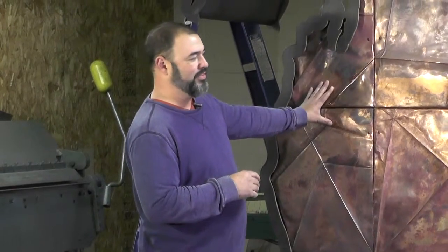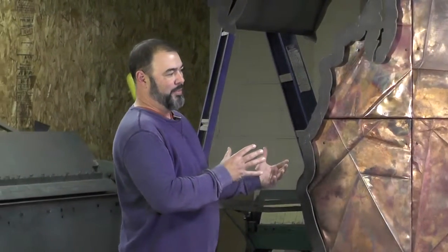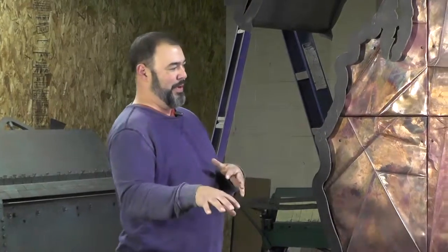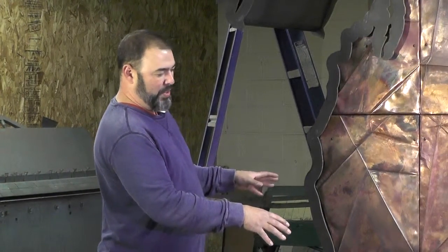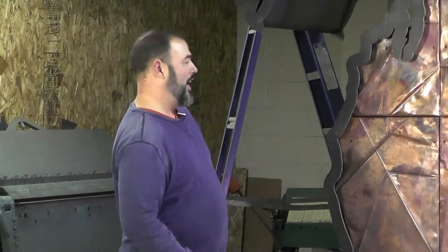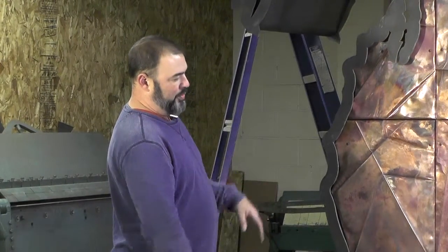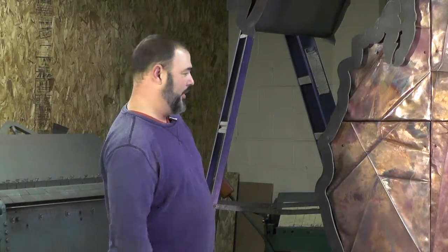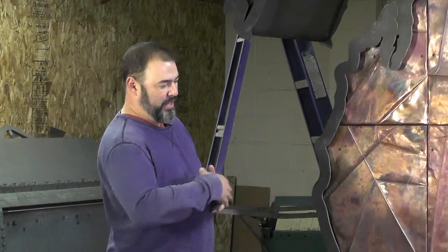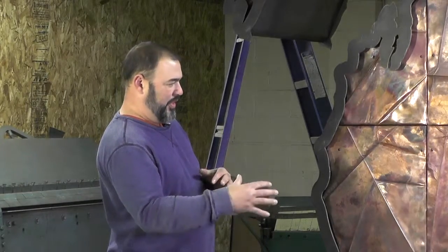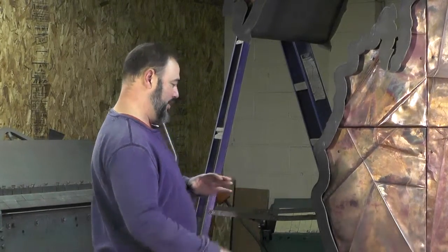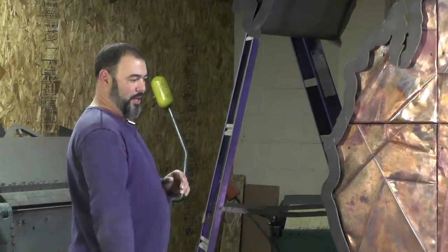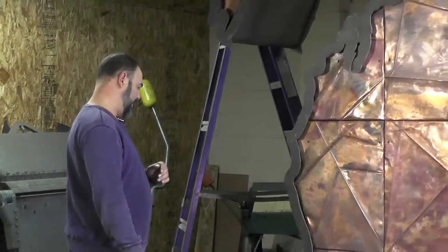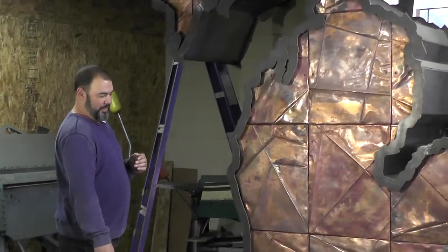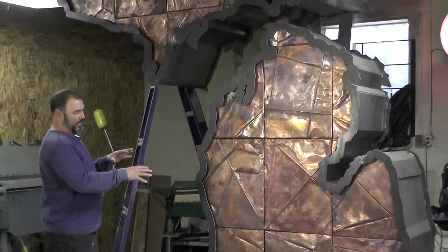Once our copper panels are finally folded, and we've got front and back completely clad in copper, all those panels will come out again, and then our Cor-Ten structure is going to go out of here and get washed down with nitric acid, which expedites the patina process. It'll bring that rusted coloration to the surface, and we wash it down with a base to stop the acid process and the patina process. Then the Cor-Ten will stay at that nice red rust coloration basically forever. And then we'll reassemble our copper panels and deliver to the site.